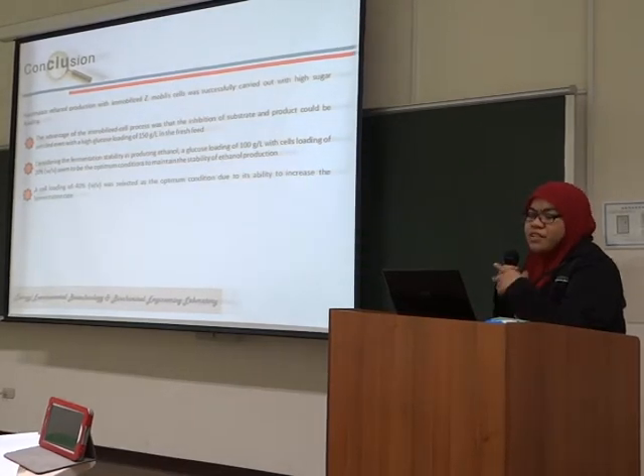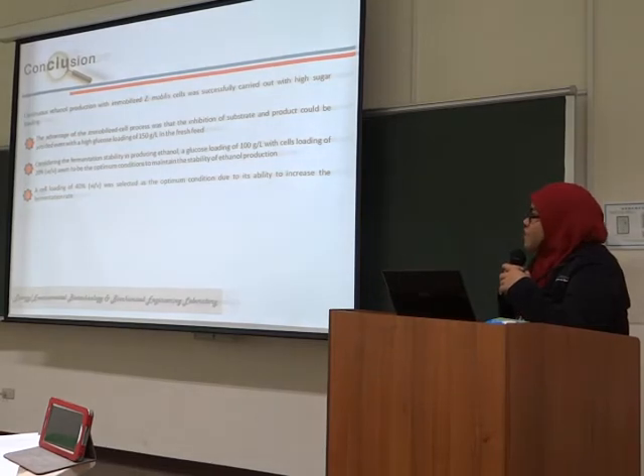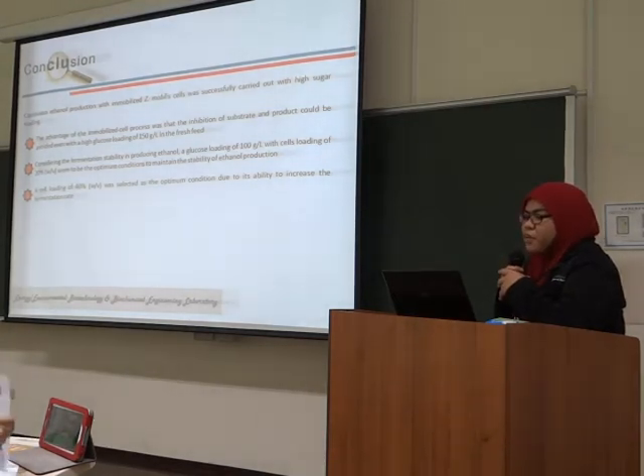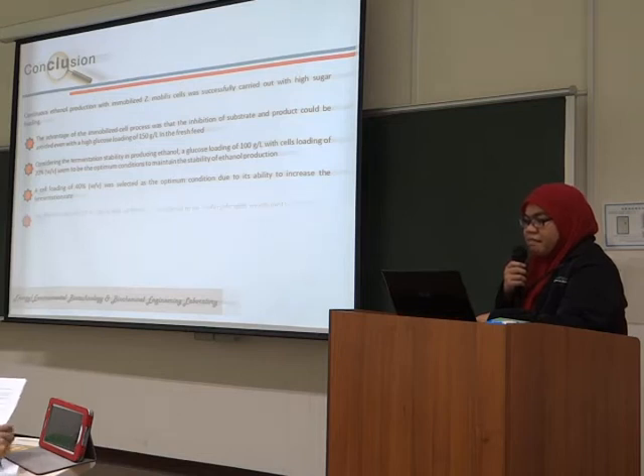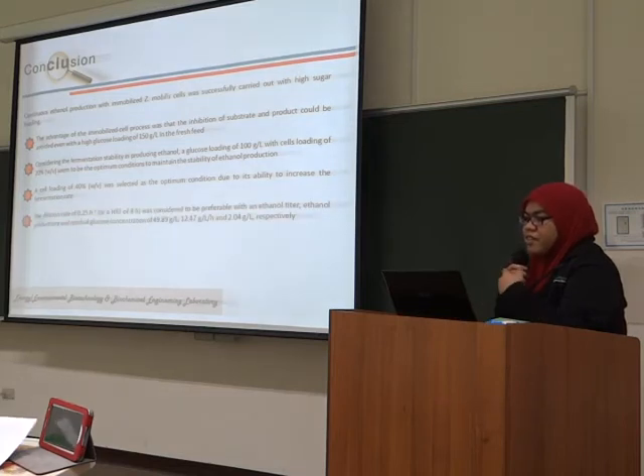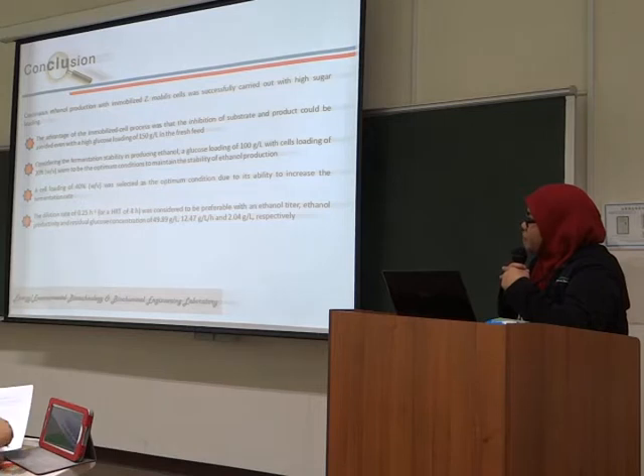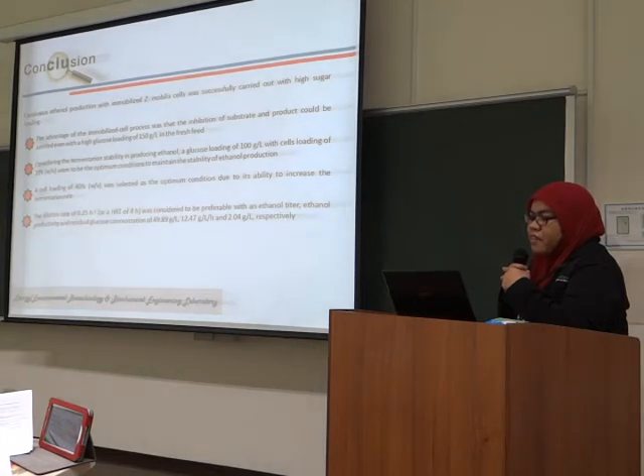And then if we consider the cell loading, 40% weight per volume was selected as the optimum condition, because it is able to increase the fermentation rate compared to 20% weight per volume. And 50% weight per volume is unnecessary, I think. And if we consider the dilution rate or hydraulic retention time, 4 hours should be considered favorable with the ethanol titer, ethanol productivity, and residual glucose concentration.